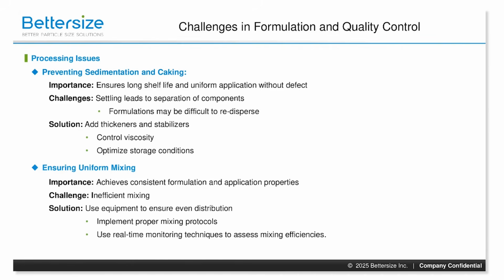Another processing challenge is to ensure uniform mixing. It's important that we achieve consistent formulation and application processes to know that all components are evenly distributed. Inefficient mixing can lead to uneven distribution of the pigments, binders, and additives, and this will affect color and performance. This is especially important in large batches, as they may present difficulties in achieving thorough mixing. Solutions include mechanical mixers to break up the clumps and ensure even distribution. Using real-time monitoring techniques to assess mixing efficiency is important, and you can adjust the parameters as needed.